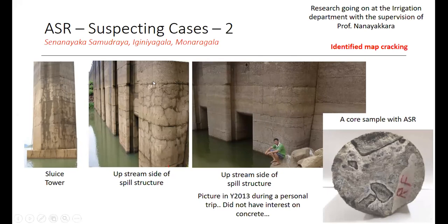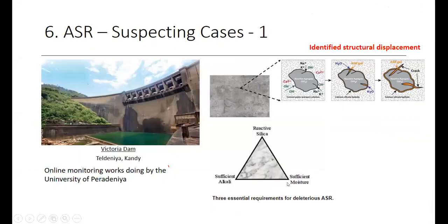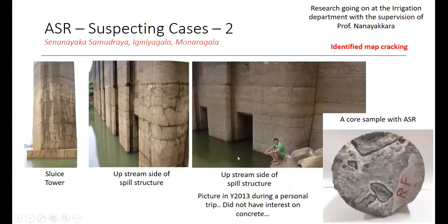Okay, so you can see here, this is the water level. Those are the cracks. You can clearly see underneath the water level we can see those cracks. So here, it needs a sufficient amount of moisture. On top of the water level, we can't see those cracks. It means it doesn't have the required amount of moisture. So those are the ASR forms.